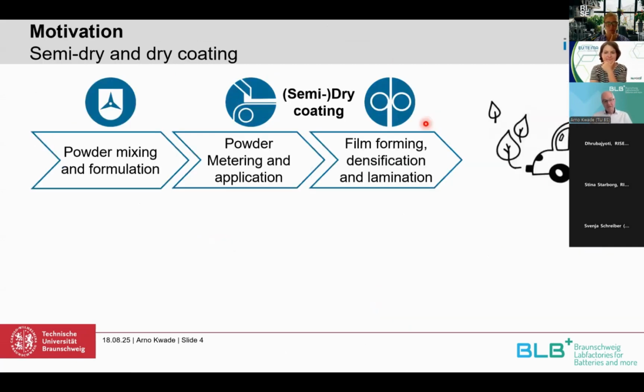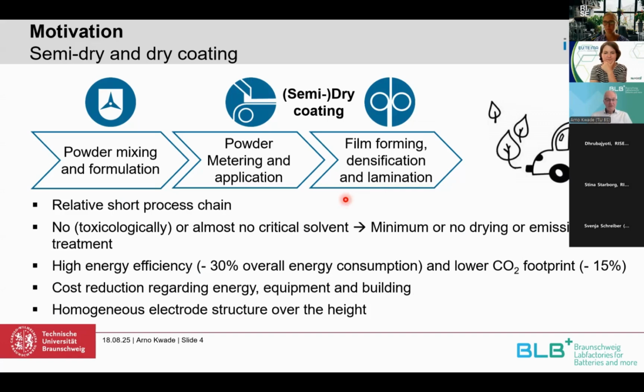That means that we have to look for dry or semi-dry coating. And by that, we not only decrease the energy demand, we also shorten our process chain. So we have a dry powder mixing and formulation, or let's say semi-dry. In a special case, then we have to meter the powder, dose the powder, which is an important step, but not really takes a lot of energy or space. And then we have the film formation, and then the lamination maybe on the current collector. And by this relatively short process chain, we can also avoid critical solvents.